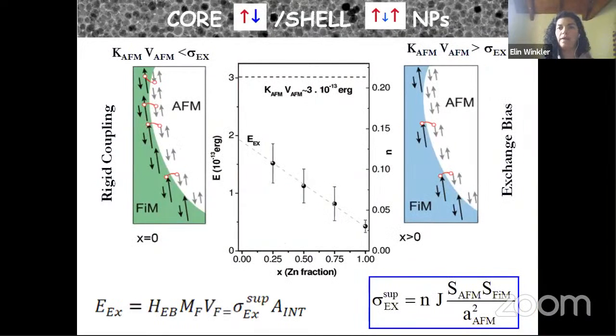So how can we quantify a little more about that? Well, we have all the data to calculate the exchange interaction, which is proportional to that asymmetry of the hysteresis field, and we observe that this is systematically reduced when we increase the zinc fraction in the shell, and when we reduce the zinc fraction, it approaches the antiferromagnetic anisotropy. And if we move in that direction, we change from the rigid coupling to the exchange bias regime. Moreover, from this value, we can also calculate the density of the exchange bonds.